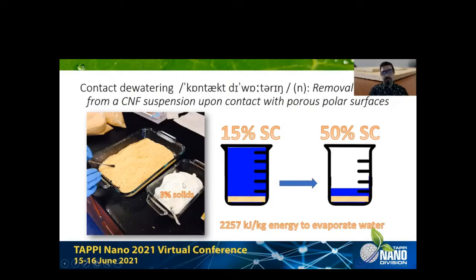That is impossible to do. But when you mix these together, the magic actually happens naturally. And this process that we now have called contact dewatering basically enables that water, which is in the form of bound water, to change into free water, and then it can be easily mechanically removed from the system. So if you compress this mixture from 15% solid, you can get to about 50% solid content. If you do it several times, you can even go to higher solid contents. And that will save a lot of energy. So I have a video here to quickly show you what we mean by contact dewatering.